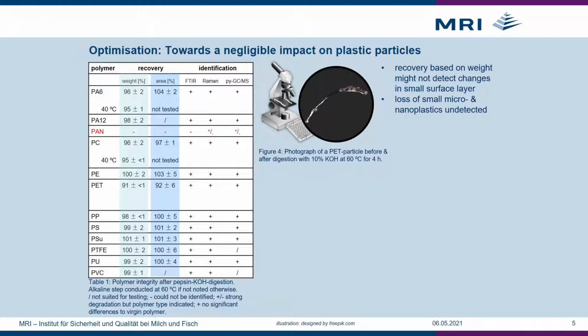Consequently, we also assessed the projected particle area, where we could observe a significant decrease for PET, so we reduced the temperature of the alkaline digestion step.